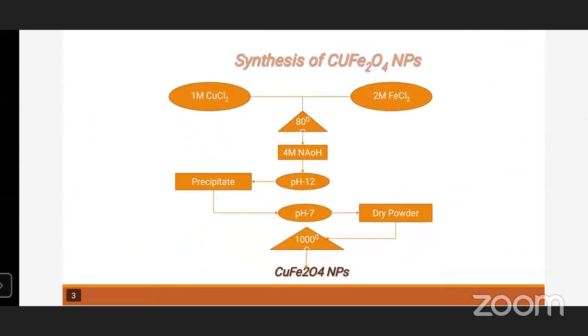Okay, then I will explain about the synthesis. How to synthesize copper ferrite nanoparticles. A 1:2 mole ratio of copper chloride and ferric chloride were taken. At a stoichiometric quantity, the precursors were blended using distilled water in a magnetic stirrer. A constant temperature of 80 degrees Celsius was maintained. And then the precipitating agent was introduced drop by drop till the pH of the solution reached 12.